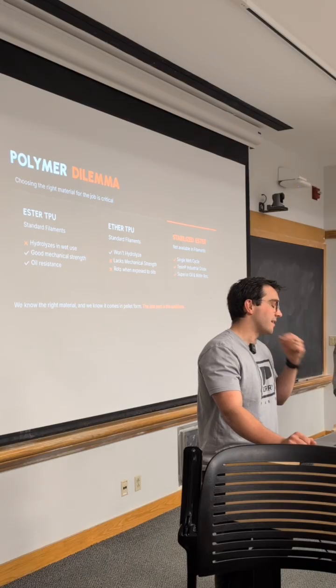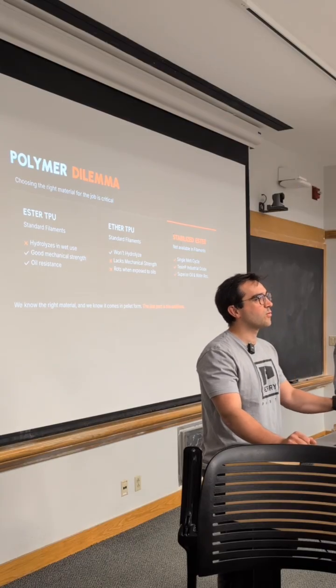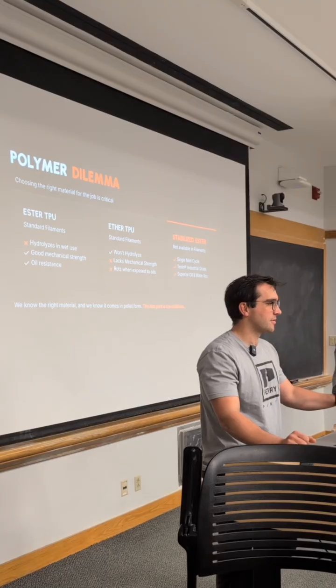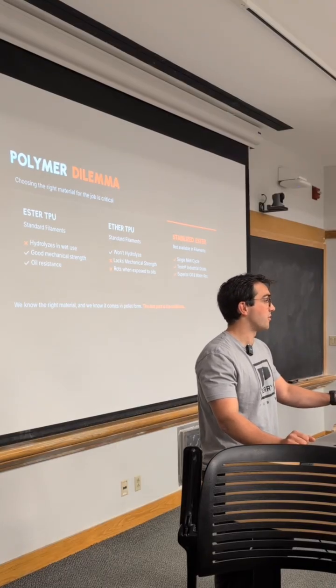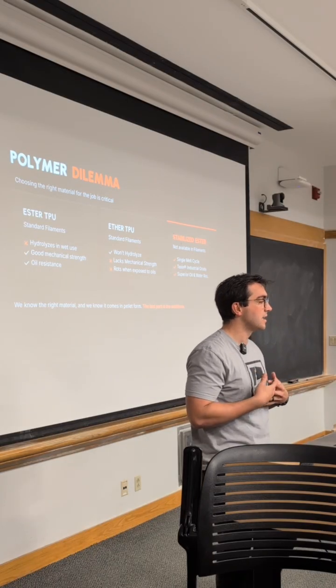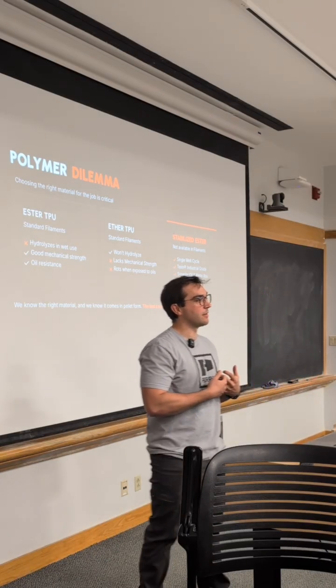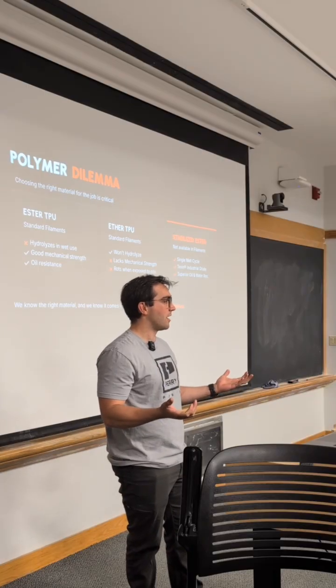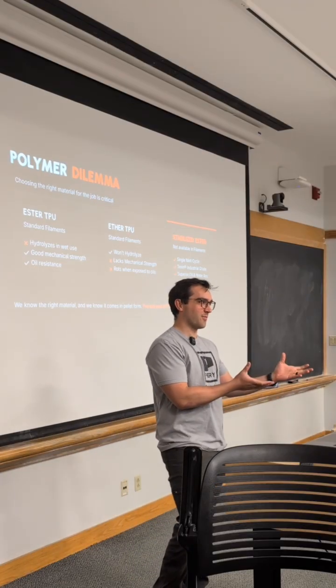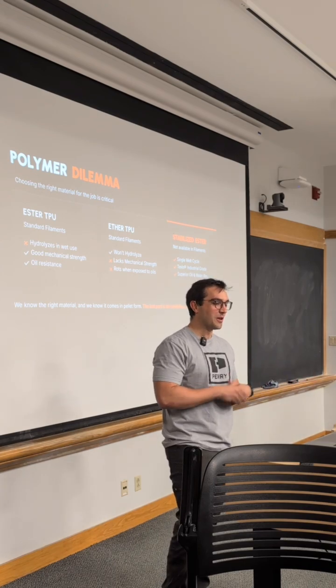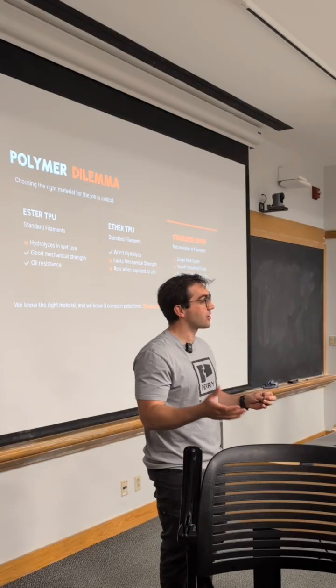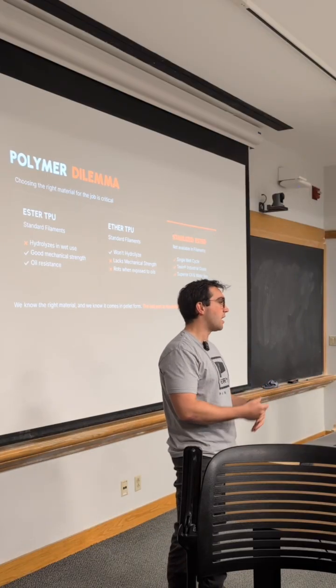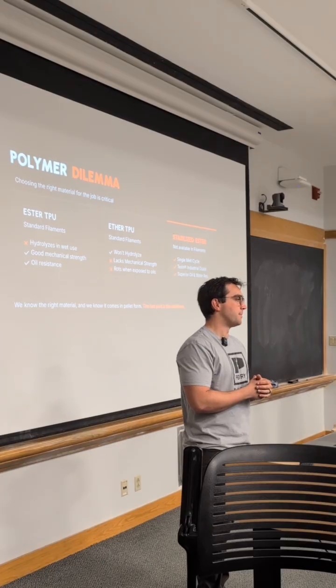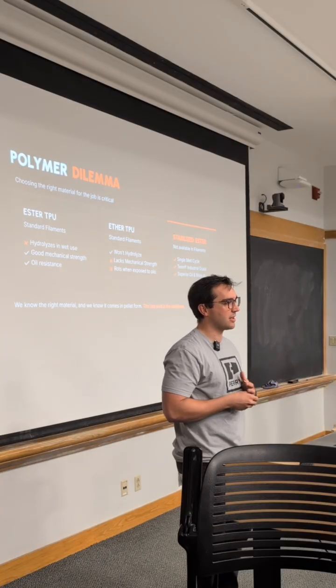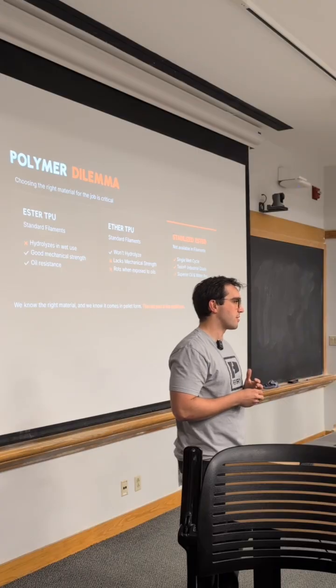So yeah, the TPUs were used for a while, 20 years ago, 30 years ago, for automotive parts like bushings and other things similar to what we're making. They were injection molded, and they stopped doing it in part because there was hydrolysis. Now, and this is all from my sales rep at my polymer supplier, with the advent of some of these stabilized esters, they're actually starting to push back into the automotive space again because it has mitigated a lot of the issues. But the main downside of a stabilized ester is cost. They're much more expensive because they kind of bridge the gap between the different grades.